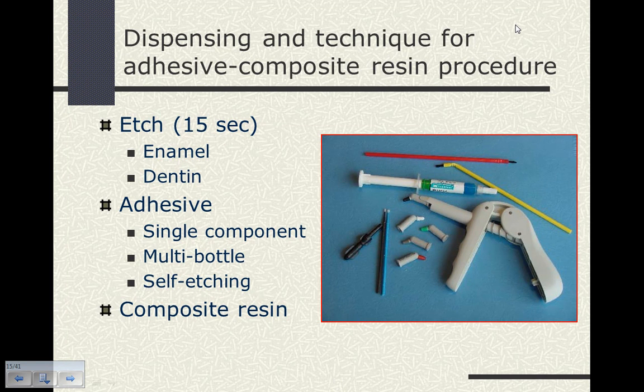When we're using these resin adhesives with composite, we're going to use the technique you've learned in the first year, and this is a review of it. We're going to be etching the enamel and dentin simultaneously for 15 seconds, rinsing for 10 seconds, then drying the tooth off. We'll then be applying our adhesive, whether it be a single component adhesive, which would be our Optibond Solo Plus, or a multi-bottle system, which would be our Scotch-Bond multipurpose, applying the primer first for 5 seconds, then air drying it, and then applying our adhesive and air thinning it, or a self-etching adhesive where we're not going to be etching with phosphoric acid. The self-etching adhesive will etch the enamel and dentin. And then we apply our composite resin, using the compules of composite resin with the shade we selected, using the compule gun, compule applicator.